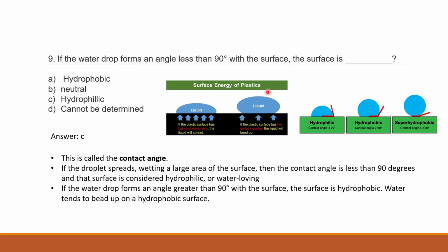Same thing, your cell also has water content, right? So the surface has to go and attach. If your surface is so hydrophobic that your cell can't even sit on it properly, then it won't attach. It will just roll away. It will die after a few days. So this is important for your wettability and your degree of attachment of your cell to the surface. This is the angle with which you determine that, and this is called the contact angle.